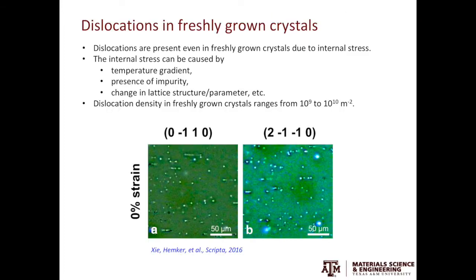First, dislocations can form in the undeformed, freshly grown crystals. Those dislocations formed due to the internal stress during the crystal growth process. The internal stress may be caused by the temperature gradient, the presence of impurity, as well as the change in lattice structure and parameters.